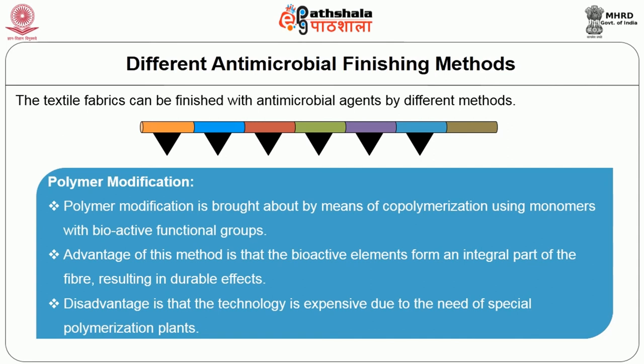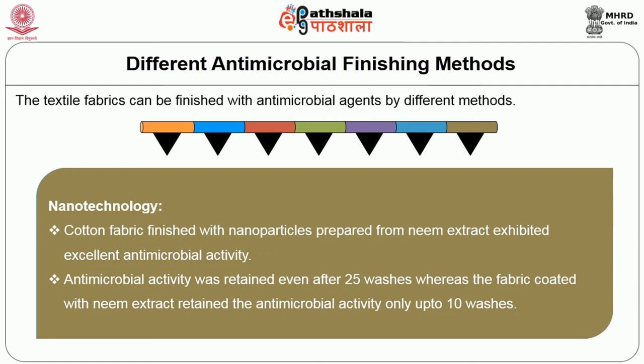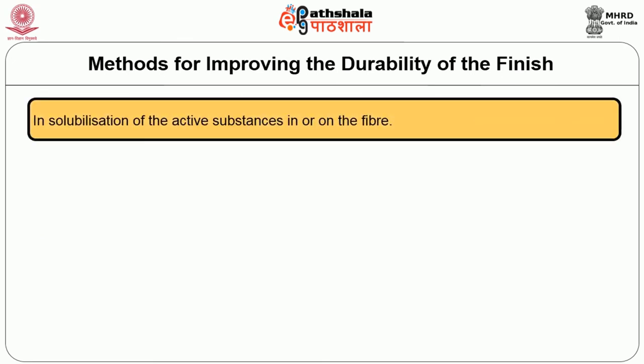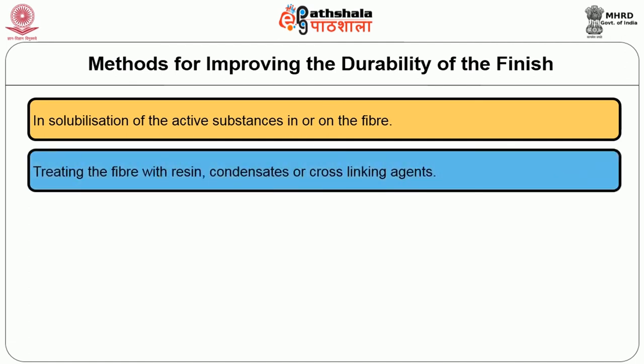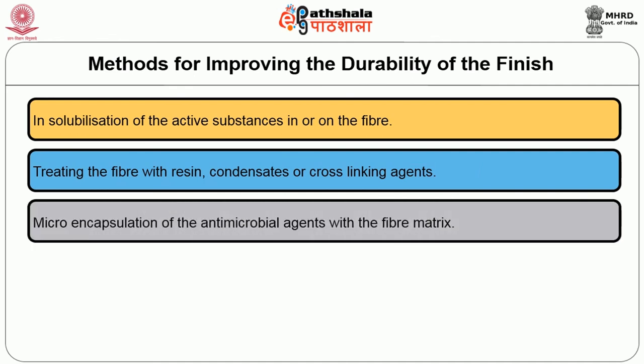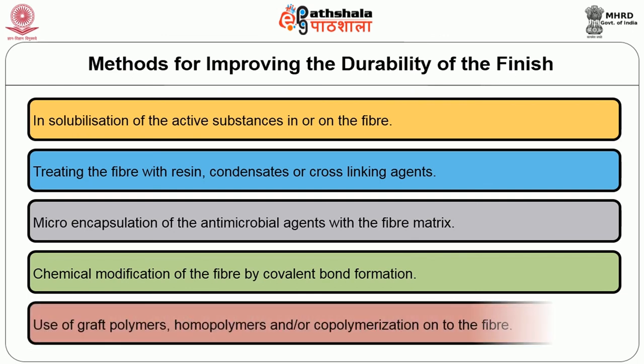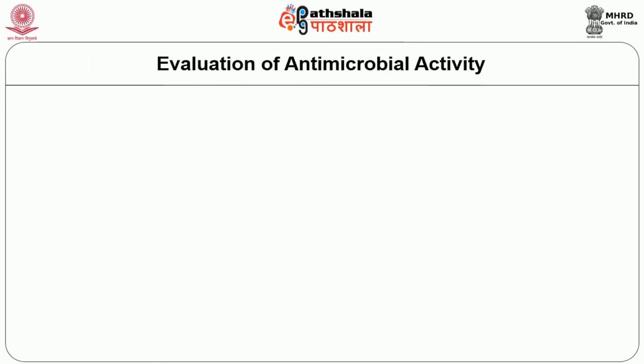In nanotechnology, cotton fabric finished with nanoparticles prepared from neem extract exhibited excellent antimicrobial activity. Antimicrobial activity was retained even after 25 washes, whereas fabric coated with neem extract retained antimicrobial activity only up to 10 washes. Methods for improving durability of the finish include: insolubilization of the active substances in or on the fiber; treating the fiber with resin condensates or cross-linking agents; microencapsulation of the antimicrobial agents within the fiber matrix; chemical modification of the fiber by covalent bond formation; and use of graft polymers, homopolymers and copolymerization onto the fiber.